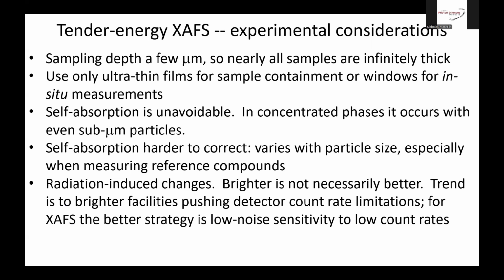Self-absorption is generally unavoidable in this energy range. In concentrated phases, self-absorption will be happening even with submicron particle sizes. So you can't get the particles fine enough to not have self-absorption. Even doing the standard approach of diluting a standard material, if your particle size is still larger than half a micron or so, the individual particles within that diluted sample will be self-absorbed. And so you can't get away from it. It's often harder to measure a good standard than it is to measure your sample for that reason.